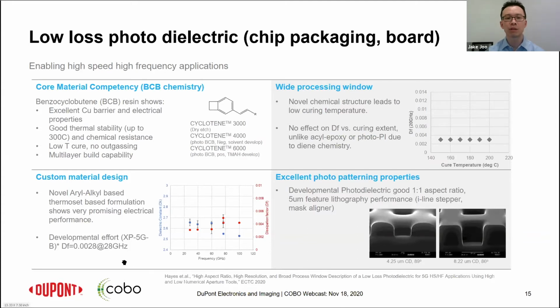One of the benefits of this type of material is that the material itself is based on diene chemistry, meaning that whatever curing temperature you run, depending on the condition, Df actually doesn't change, compared to some different types, such as acrylic, epoxy or photo polyimide, that have different curing conditions that may end up delivering different Df values. This one also has good photodielectric patterning capabilities that can be used with an i-line stepper or mask aligner as well.